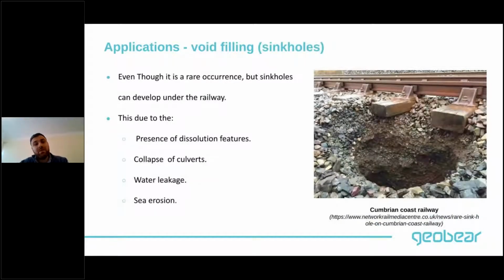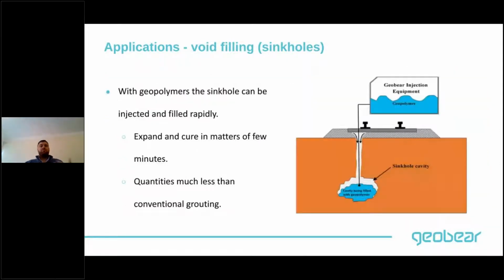Another obvious application of geopolymers: we can use geopolymers to treat sinkholes. Sinkholes on the railways are quite a rare occurrence. They don't really occur that often, but when they do, it can be due to a number of reasons, for example, the presence of dissolution features, the collapse of culverts, water leakage, or even seawater erosion. And you can end up with a quite difficult sinkhole to treat. What can we do about this? Well, we can start injecting the geopolymers into the sinkhole cavity to fill it completely.